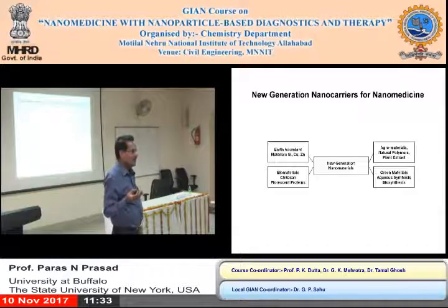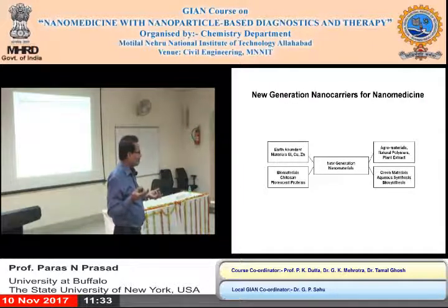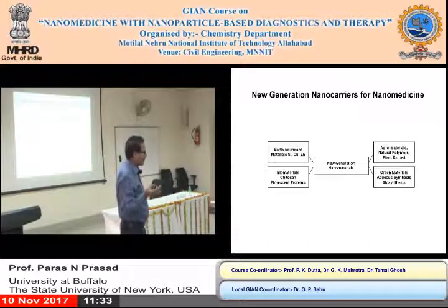survive. They're called extremophiles. So we took these extremophiles and their cells, we injected cadmium salt, a cadmium source. We injected a source of sulfide or selenide, like sodium, and they synthesize cadmium sulfide or cadmium selenide nanoparticles.